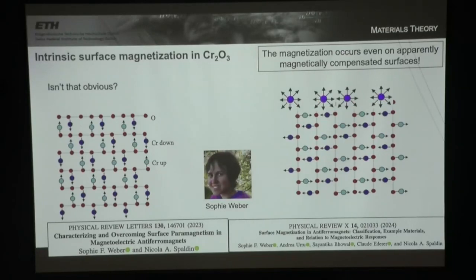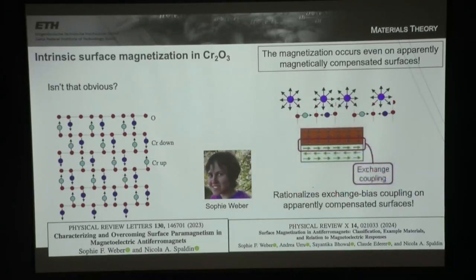And I was super excited about this because it's something that's annoyed me for decades, actually, since I was a PhD student, that many of these surfaces that appear to be magnetically compensated have this property of exchange bias coupling, that we talked about right at the start, an important application of antiferromagnets. And if we just look at the cartoon that I showed you, we'd not expect that, right? Here it looks like the exchange bias coupling is coming from the uncompensated spins at the surface. And so now we understand why these apparently compensated magnetic surfaces are showing exchange bias coupling. So we were very excited about that.